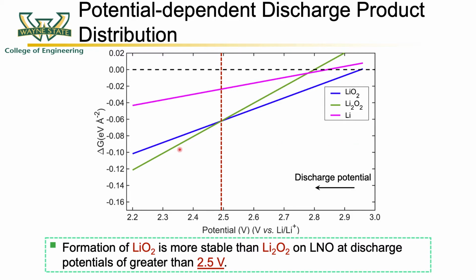These theoretical insights are then converted into a phase diagram where the free energy of formation of LiO2 and Li2O2 as a function of discharge potential is studied. It is observed that beyond a discharge potential of roughly 2.5 volts, the formation of LiO2 is more stable than that of Li2O2.